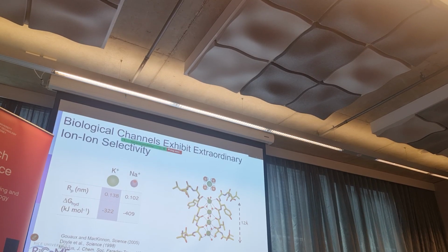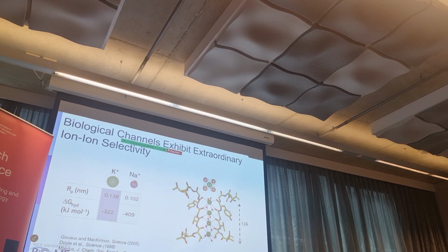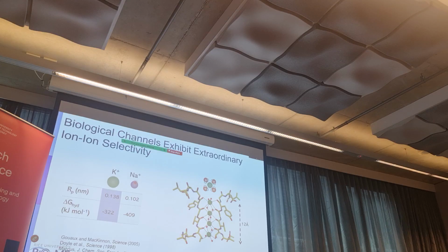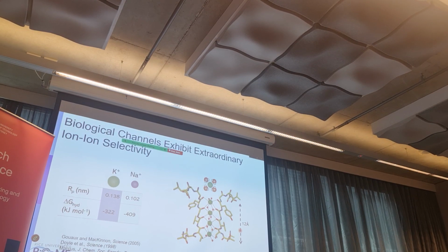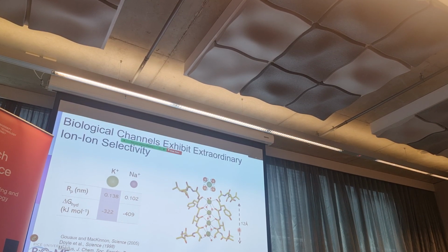The selectivity is more than 1,000 - for every few thousand potassium ions that go through, only one sodium will leak through the membrane. And how does it do it? It's a very thin membrane, if you can call it that - only 12 angstroms, 1.2 nanometers. I tell you that if you try to engineer it, in reality it's very, very difficult, very, very thin.